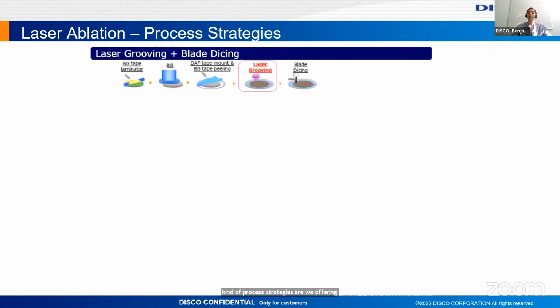Focusing on laser ablation, what kind of process strategies are we offering? The main application in the semiconductor industry for the laser is still laser grooving, followed by blade dicing. More or less the laser is used to remove some sensitive top layers or PCM structures like metal structures, gallium nitride that is hard to dice with the blade. You open the dicing street for the blade cut, and then cut the bulk material by the classical blade dicing approach.